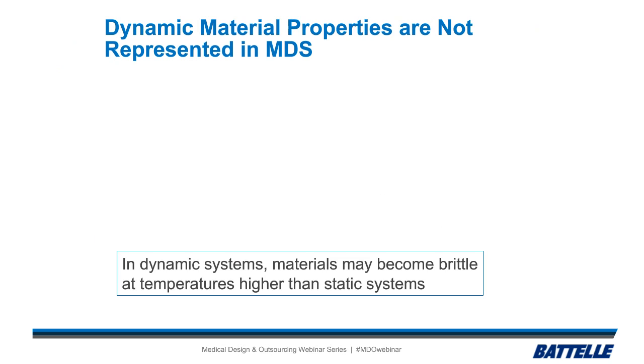Next, dynamic material properties are not represented in material data sheets. So in dynamic systems, and I'm talking about anything that oscillates or vibrates, the oscillation or vibration can actually move the glass transition temperature. So much like a material can become brittle when it becomes cold, it can also become brittle if you vibrate it fast enough. So if you think about silly putty, if you roll it into a ball and throw it very fast, it stays as a solid, it bounces back up and you catch it, but if you put it on the table, it flattens out. So that's this, where if you hit something fast enough, it acts like a solid, and it actually could be a brittle solid at that point.